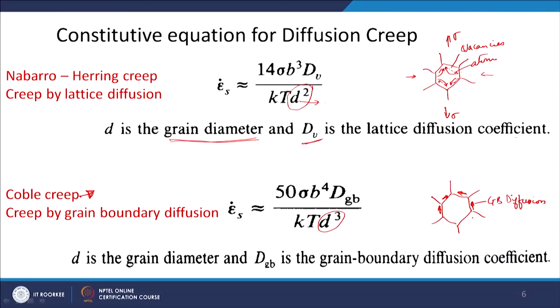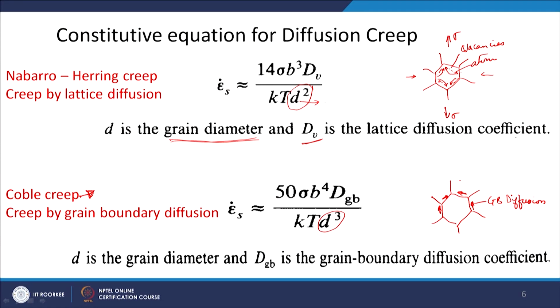So you will see that for smaller grain size, Coble creep is the important diffusion process, because you have more grain boundary for diffusion to take place. Whereas for the coarse grain of the same material, Nabarro-Herring creep will be the dominant creep process, where the diffusion will take place through the lattice. So there you can see very subtle changes taking place in the constitutive equation, based on what type of deformation mechanism is operating in the material.